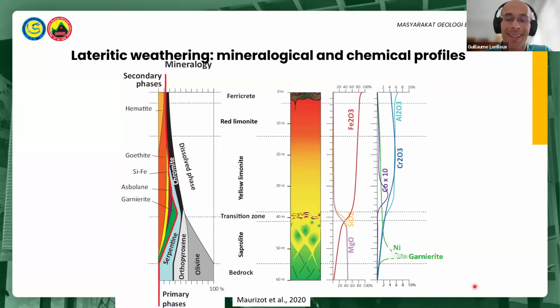The dissolution of the peridotite silicate minerals by acid meteoric water is associated with the removal of mobile elements, mainly silica and magnesium. As you can see on these curves here, the concentration of magnesium and silica decreases upwards. The least soluble elements, iron, aluminium, and chromium, are more and more concentrated going upward by residual enrichment. Very few clay minerals form as a result of the low aluminum content of peridotite. Nickel, cobalt, and manganese have intermediate solubilities and are enriched in saprolite and/or in the lower part of the limonite.